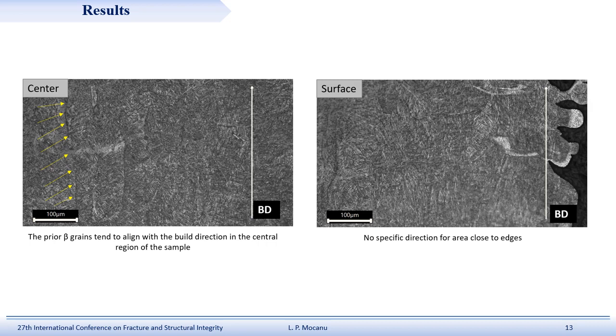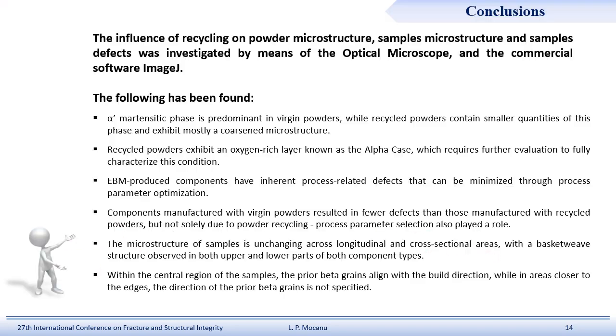Something interesting we saw is these prior beta grains, which tend to follow the building direction. This is true only in the center of the specimen, as can be seen here, while closer to the edges, so in the surface, these prior beta grains have no specific direction.